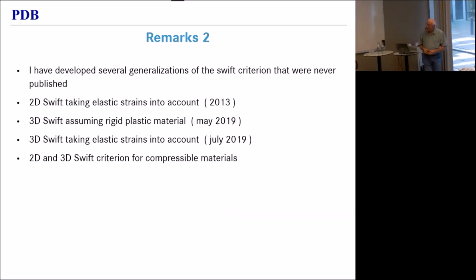Second set of remarks, you can generalize this as much as you want. We have written the equations for a 2D Swift, taking the elastic strains into account. We've done a 3D Swift assuming rigid plastic material and a 3D Swift taking elastic strains into account. And you can even do it for compressible materials. So you can do it for plasticity theories that allow permanent volumetric straining. Materials that have a plastic Poisson coefficient that is not equal to 0.5. And we're going to implement all that, right, Marion?